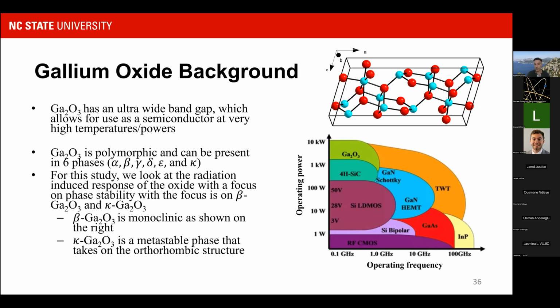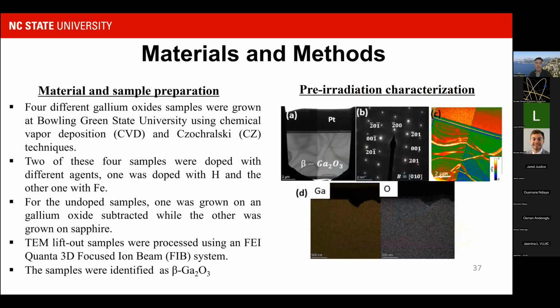The one thing that we know about gallium oxide is that it's polymorphic. It can exist in 6 phases, but the most stable one from a thermodynamic point of view is the beta one. So we have samples of gallium oxide that were grown by a collaborator at Bowling Green State University through different techniques. And 2 of them were even doped with different dopants, H and Fe, which has an effect on the gap width, basically.